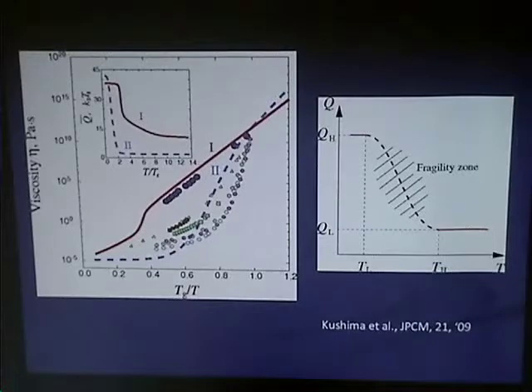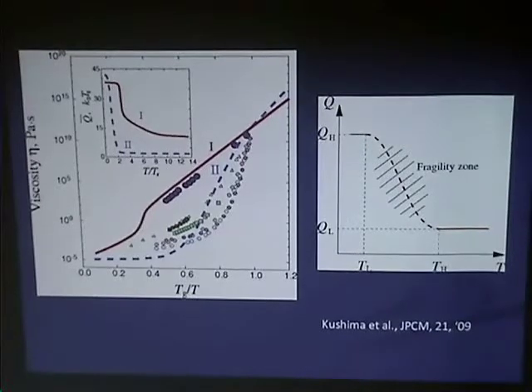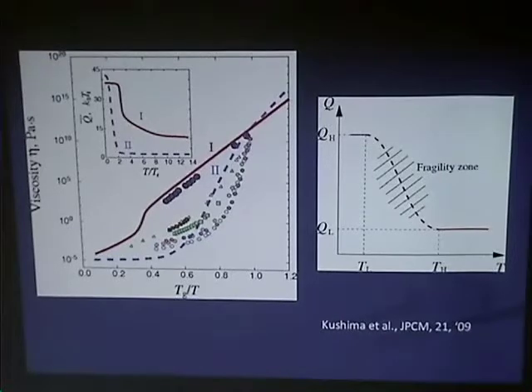So it seems, despite the very different nature of the measurements, and this is the weird thing - as you make the film smaller, down to very small sizes where you still have good integrity films, the top plateau value actually comes down to the high temperature plateau. The gap closes, they go level. As if you associate the plateau with collective motion in an Adam-Gibbs framework, it's as if all collective motion had somehow disappeared. It's curious - anyway, the plateaus come together for some reason.